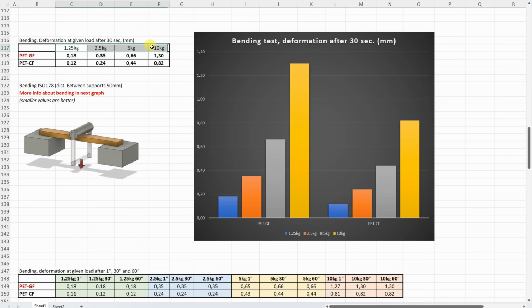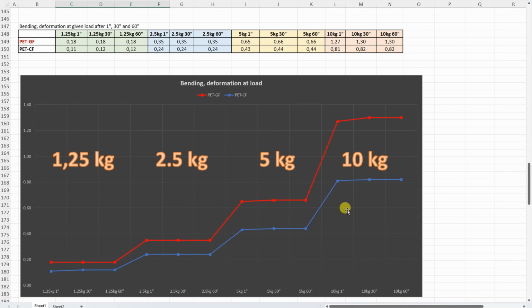This is the deformation under these loads after 30 seconds, and smaller values are better, so this means less deformation on PET-CF. But this graph is more interesting, where we can see the deformation under these loads after 1, 30 and 60 seconds. And here you can see that almost in every case this is completely horizontal line. Only on 10 kg I can see some bigger change here with the glass fiber version. But after this it became quite horizontal, so basically both materials are quite stiff. And this is not big load for these filaments.